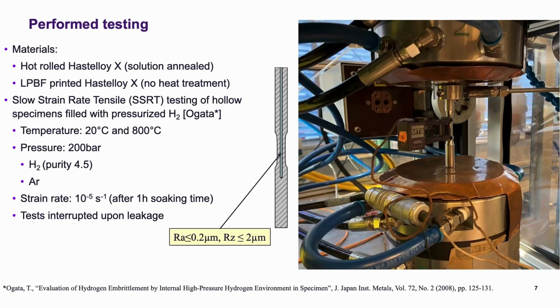And what I want to highlight here, I mean, it's been said before that this test method has its drawbacks and challenges, and usually it's said that it's a cheap, safe screening method. But from my perspective, maybe the most interesting thing about this testing method is that we have the freedom to go to as high temperature as we want, and also have high heating and cooling rates. So we can also have a strain measurement at high temperature. So it's quite straightforward to use a normal TMF test rig and test a specimen with hydrogen inside. Or I shouldn't say it's straightforward because I haven't done it yet, but you don't need any large investments like you would need for some other testing methods.